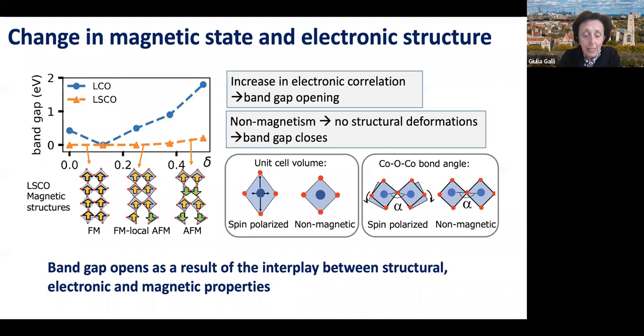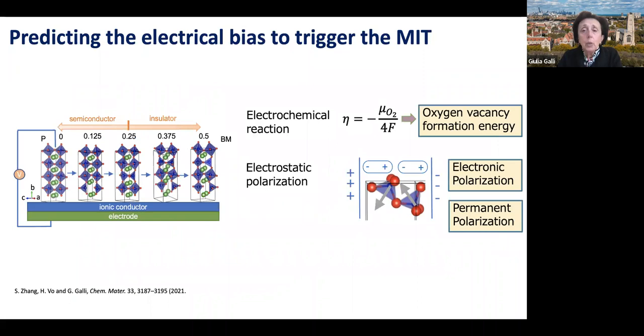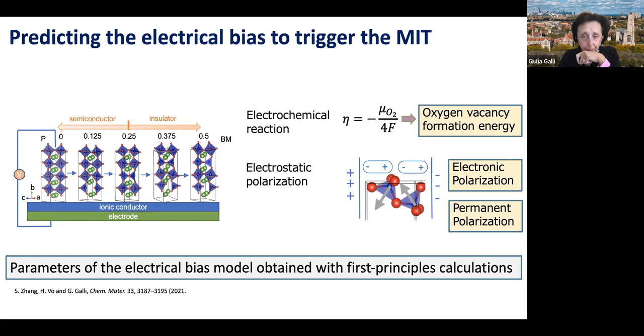And once we understood that, and we were able to compute the oxygen vacancy formation energy, the electronic polarization in the system, and the permanent polarization, we came up with a model with parameters completely determined by first principles to understand how to predict the electric bias to trigger the metal-insulator transition.